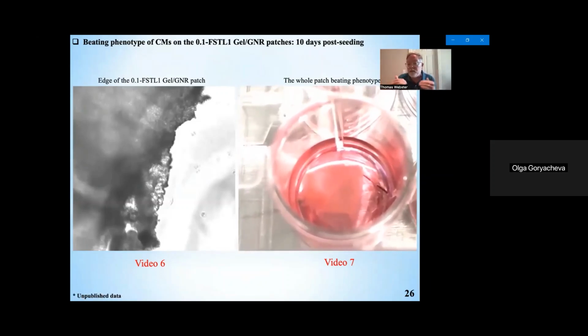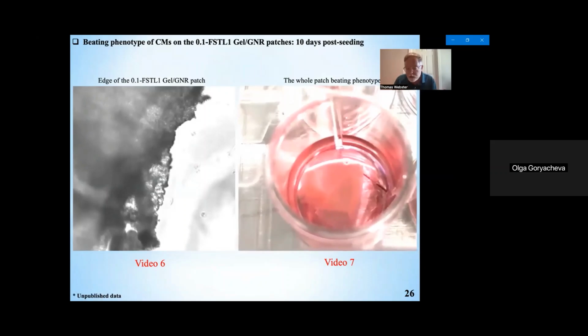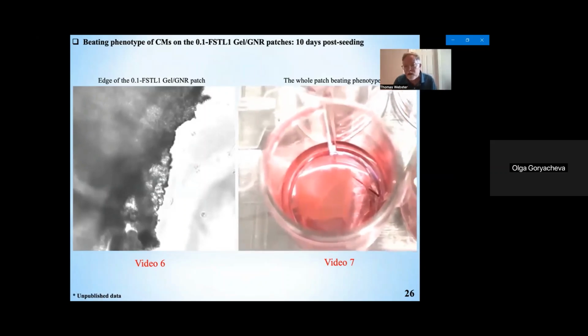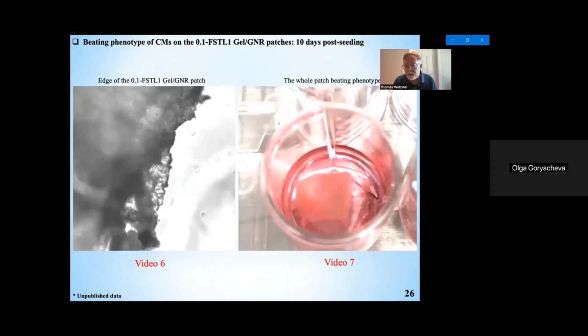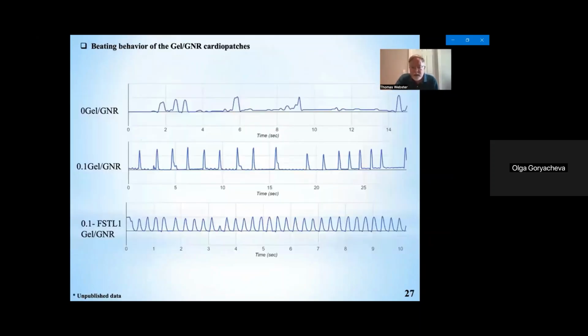And on the control samples, gelatin samples only, which don't have the graphene nanoribbons or any conductive material, we don't see beating that occurs at all. So we're very happy with this whole patch beating phenotype. We've also looked at the electrical activity, and you can see that we're getting relatively good electrical activity. Remember, one of the problems with, for example, pure gelatin is you don't get a normal beating that occurs, and you need a beating that occurs similar to the natural heart itself. So we're able to get that when we have 0.1 graphene nanoribbons with our gelatin.